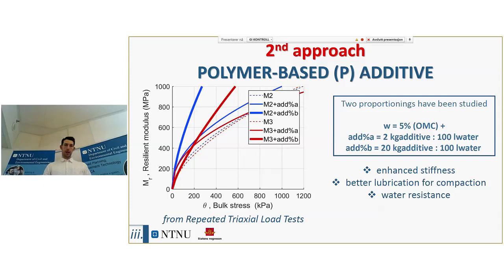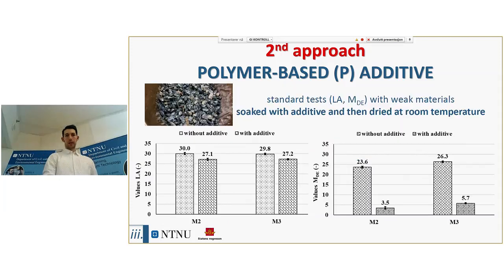results in the laboratory did confirm that the use of this polymer-based additive was effective, and we also investigated the coating effect provided by the use of this additive. That is to say, we soaked the rocks with this additive. We wait the necessary hours, the necessary time for the additive to properly bond on the surface, and then we made the standard test.